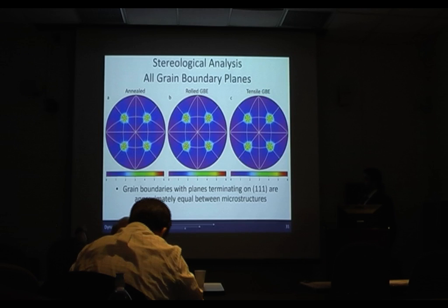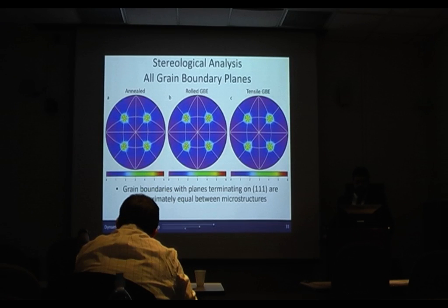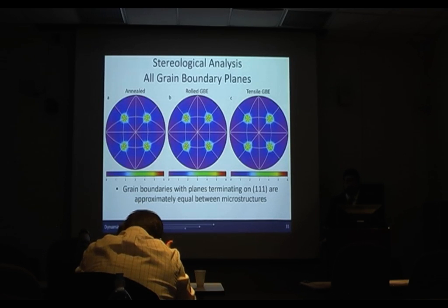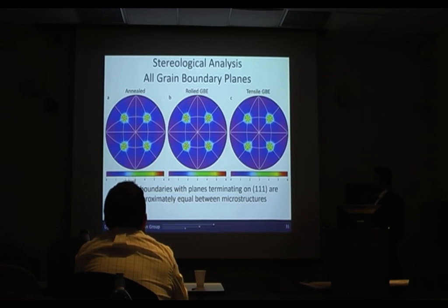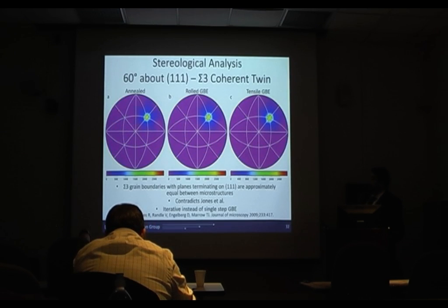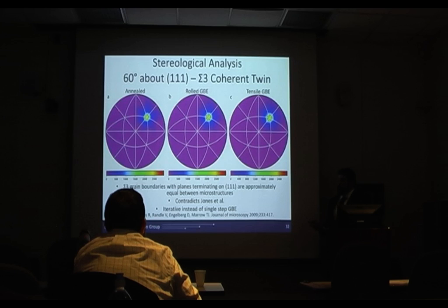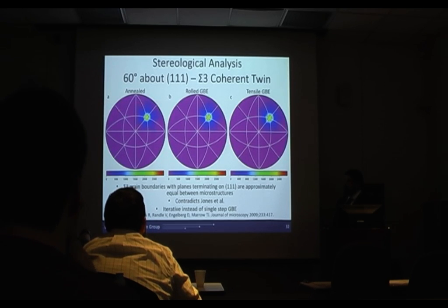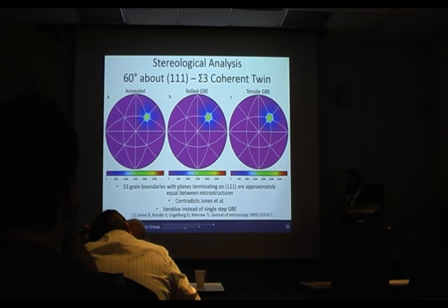Moving on to the stereological analysis, we were somewhat surprised to find that we actually had the same number of grains terminating on 111 in all 3 microstructures. This is not what was shown by Dr. Jones. And when we look at the 60 degree about 111, we actually have a much higher fraction of sigma 3 segments, denoted by about 2,800 MRD compared to his reported value in the range of 1,000. But again, they're the same across all three microstructures, which is not what he showed. There was a follow-on work by Randle where they noted something similar in only the tensile, where when they iterated it, they saw that it again returned closer to what the annealed was, but it still wasn't quite identical, and they didn't look at the rolled condition.